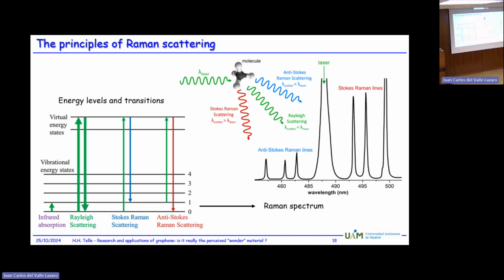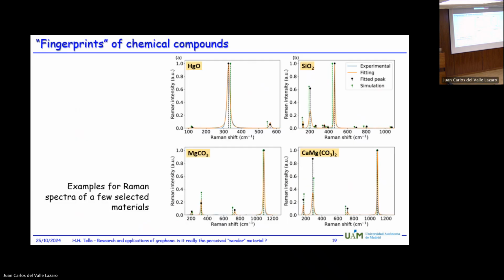And that actually gives you a spectrum, which has the very strong elastic scattering peak, and then some Raman peaks in the Stokes and anti-Stokes, meaning that you start at the ground state or you start at an excited state. And from these individual peaks, you can identify what material it is. Here's just a handful of examples where you can immediately determine what the material actually is. And because these signals are linearly proportional to the number of particles you excite, you also can get some information about the concentration of these materials.